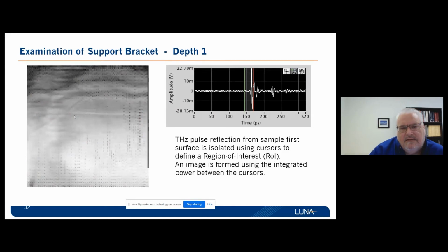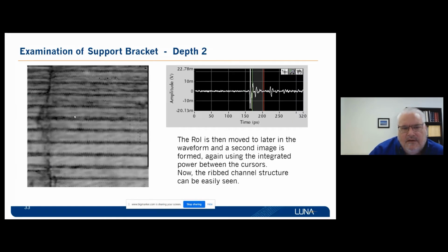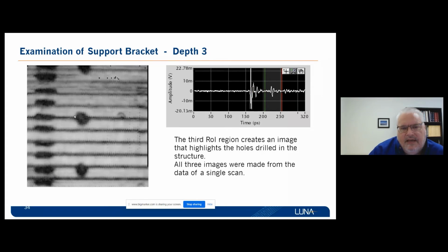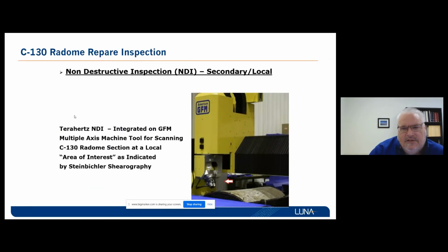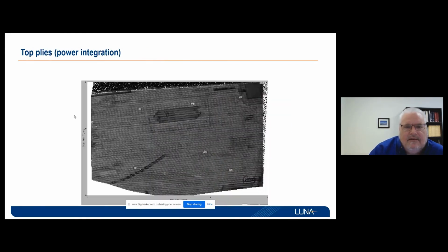This is just showing several C scans made at different depths of panels. So depth 1 showing no particularly interesting features, depth 2 showing rib structures within the panel, and then a seam structure indication over on the left-hand side. Depth 3 actually showing holes and voids that were intentionally put into the panels. And this was then automated onto a system to look at C130 panels here, where the terahertz system was integrated into the tool.